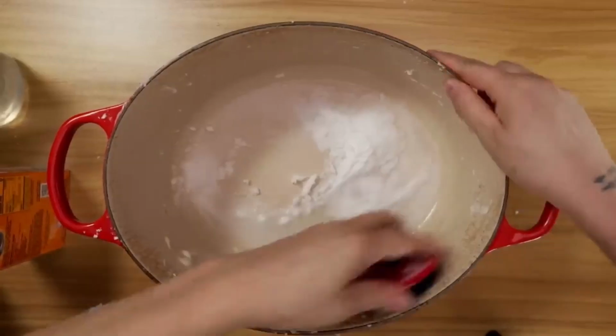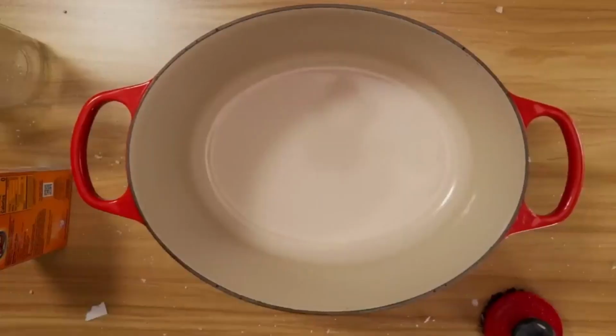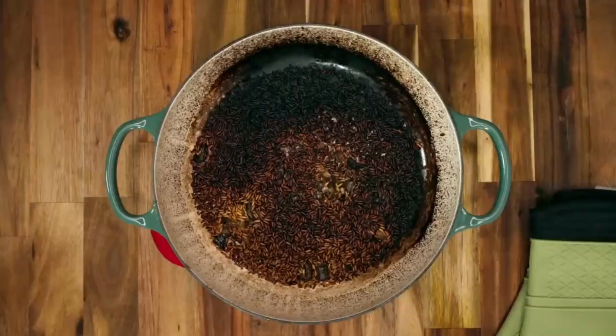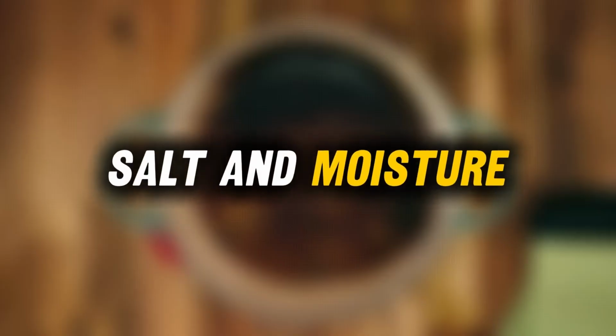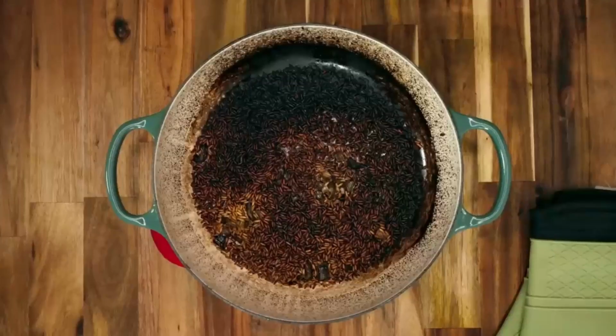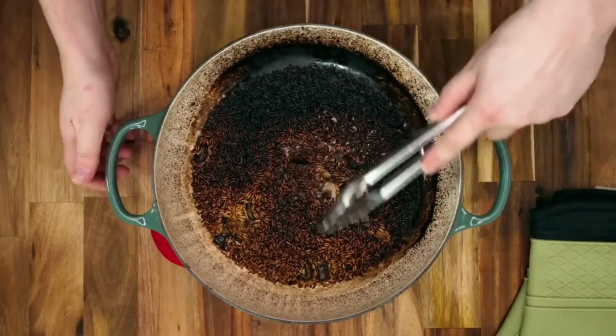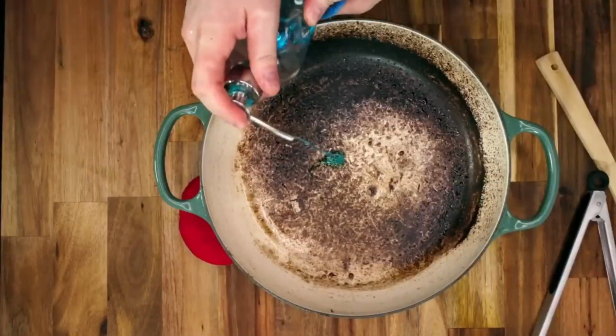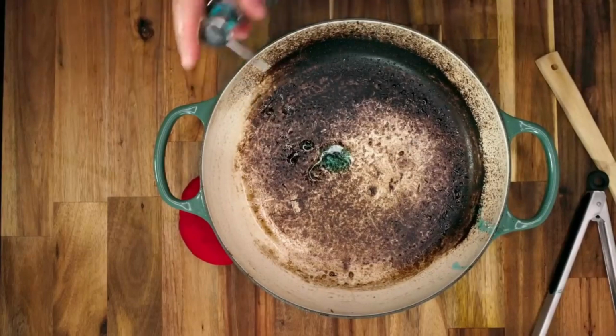Those hairlines spread with heat cycles like cracks in a windshield. Where the glass fails, iron can rust and leach, and porous cracks trap sauce, salt, and moisture. That pocket can harbor bacteria and give off flavors on your next cook. Manufacturers warn against long acidic simmers once enamel is damaged.